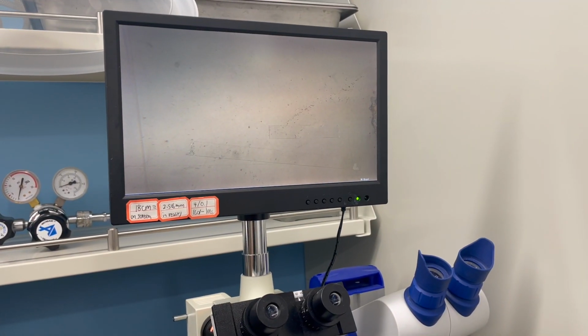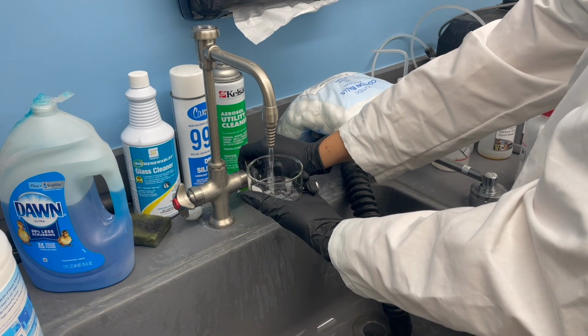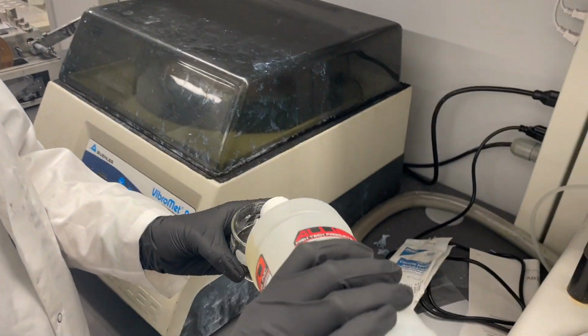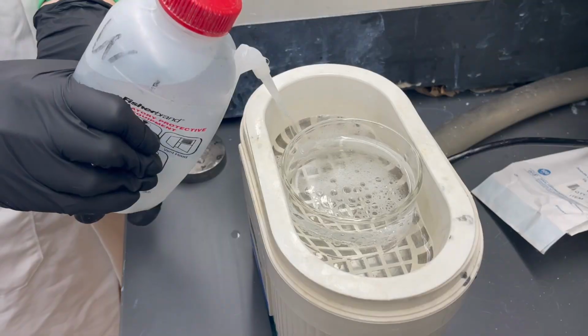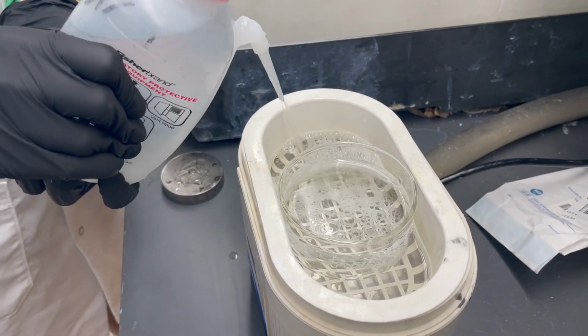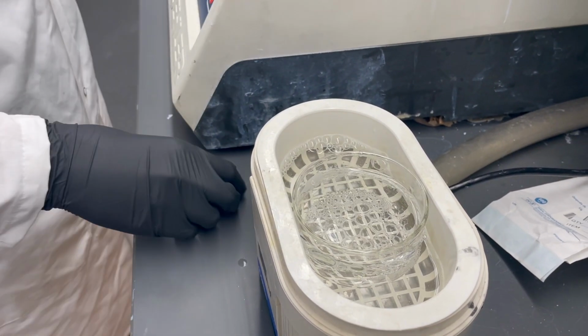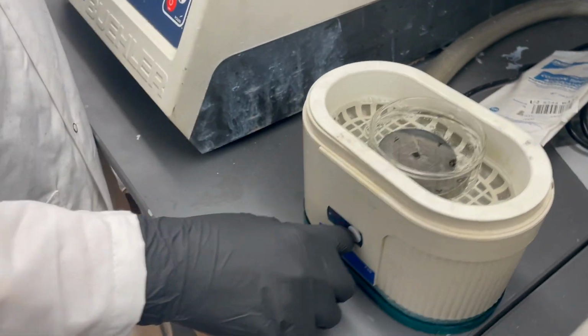Check for a mirror finish in the optical microscope. Now we will clean the sample to prepare for final polishing. Fill a small dish with water and a few drops of microorganic soap. Put the dish in the ultrasonic cleaner. Fill the basin with water and put the sample into the dish. Press the start button for a 5-minute cleaning cycle.